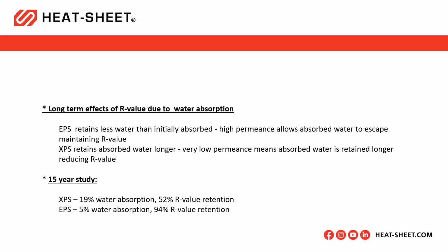So any water that does make its way in there long term actually gets trapped in there much longer because of its low permeance. As long as the water is sitting in there, it's reducing its R value. There was one study where samples were buried for 15 years. It showed on average that the XPS samples had 19% water absorption and retained only 52% of its R value. With EPS, it had 5% water absorption and retained 94% of its R value. So this is all indicative of the permeance properties of these insulation materials.